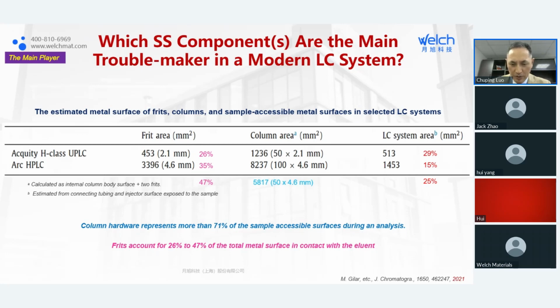In the previous slide, people used a 4.6 ID by 50 millimeter column. I used this data to make the same calculation here. The frit occupies about 47%. It's not 96% as in the previous one. But nevertheless, the column set contributes the most surface area. That means any corrosion that happens in the system, the column hardware will contribute the most.